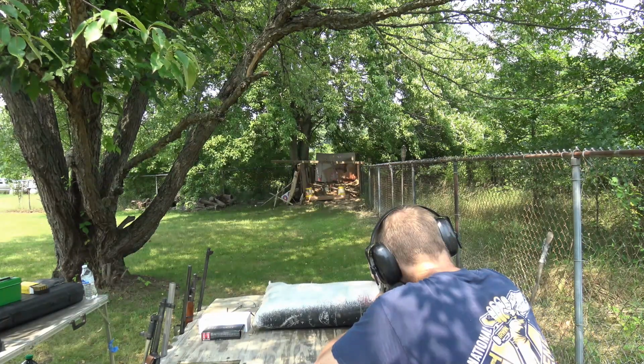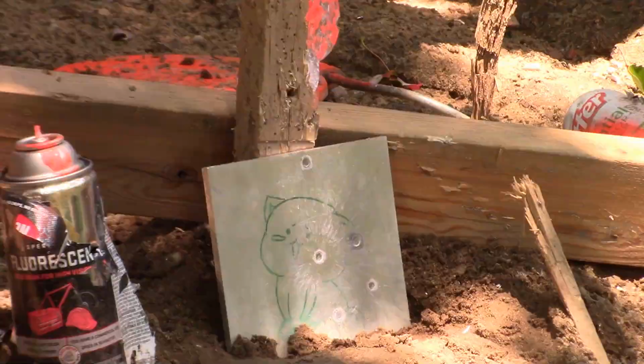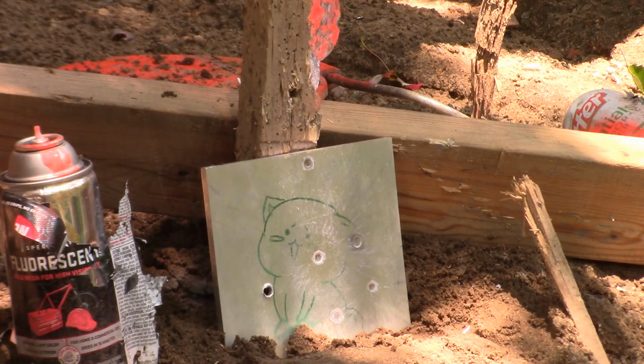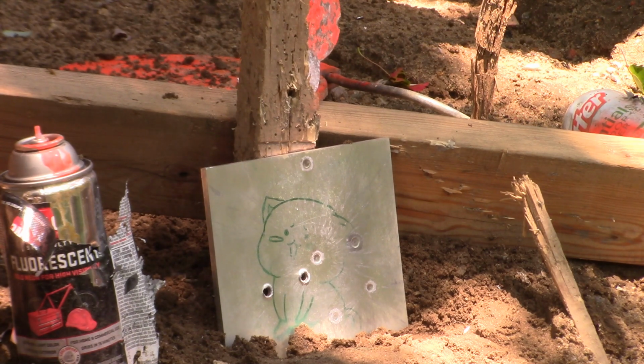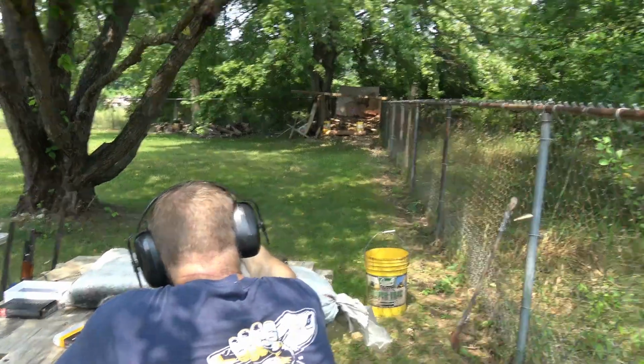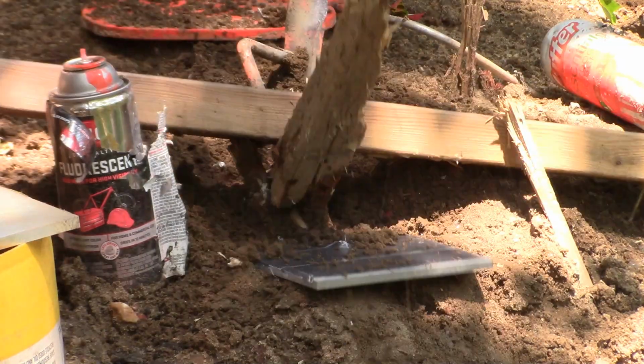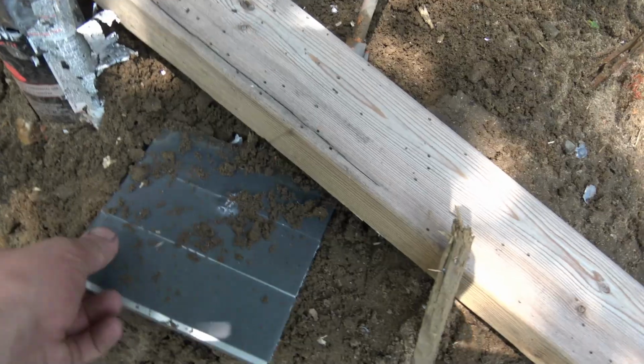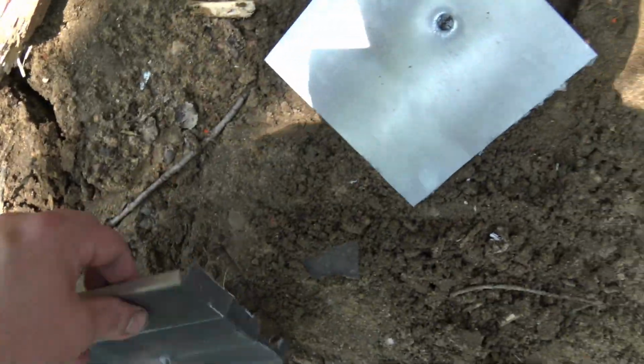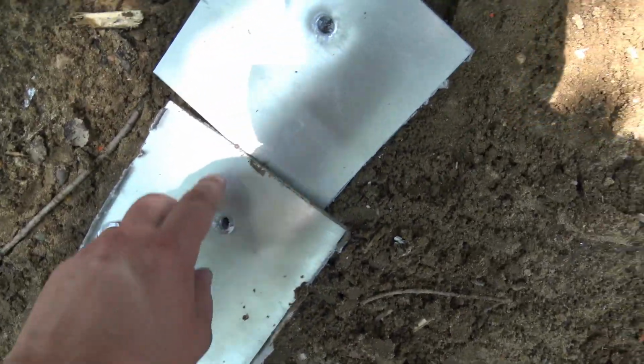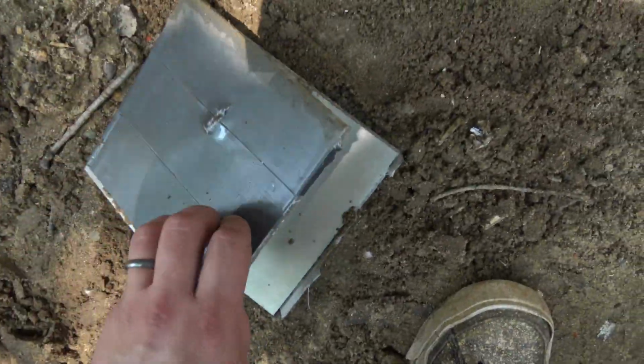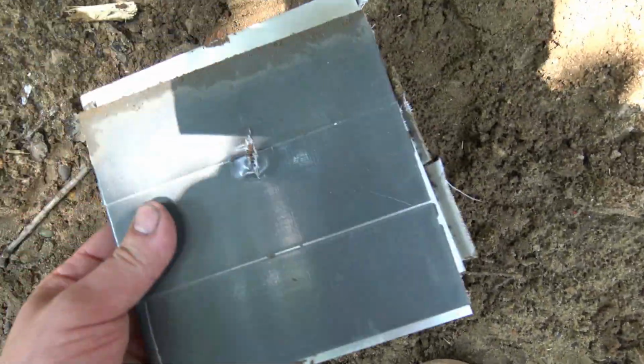Okay, now let's look at some of the rifle tests. The single layer was unable to stop the 55 grain Full Metal Jacket 5.56, and you can see how easily it passes through the single layer. I then tried the plate that had 2 1/4 inch plates duct taped together, bumping it up to a 1/2 inch of material, and as you can see, the 5.56 made it through that one as well.